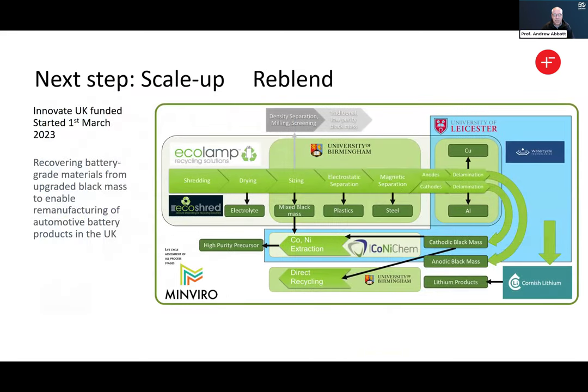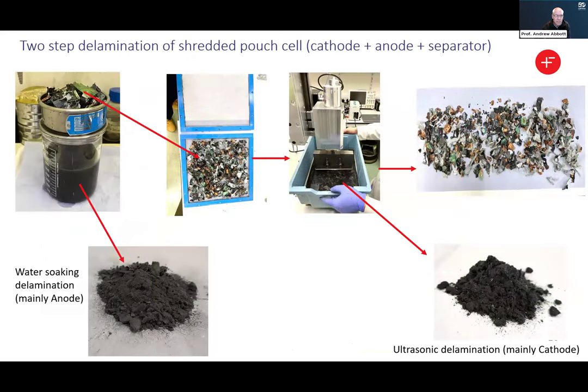We've got a project here in the UK called Reblend, where we are producing a pilot scale process. Again, what we're trying to do here is not produce black mass, but to separate out our active material. And we're using this ultrasonic delamination with our material. And rather than fine shredding, we're doing very, very coarse shredding. And what we're able to do is to separate out our anode material very simply, and that's relatively pure.